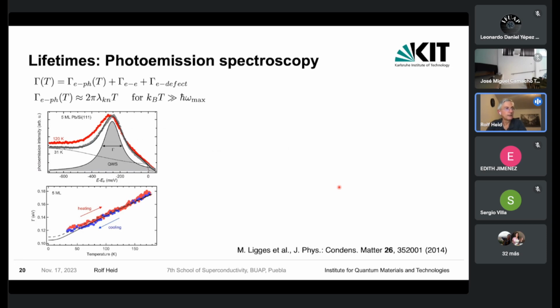Now, a last slide on this topic I show here, and that is related to the fact that one can also do photoemission spectroscopy on this type of thin metallic films and analyze certain electronic states. And in particular, one can measure the line width of such an electronic state as a function of temperature. And the data are shown here in the case of a 5 monolayer lead film on silicon 111. And you can see here a nice linear behavior in some temperature range of this line width.